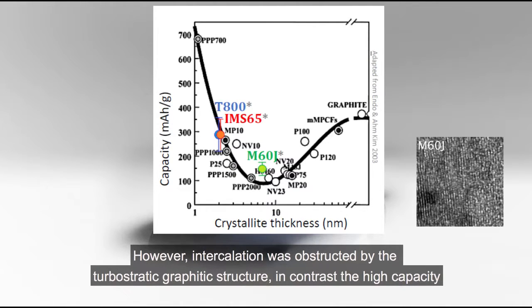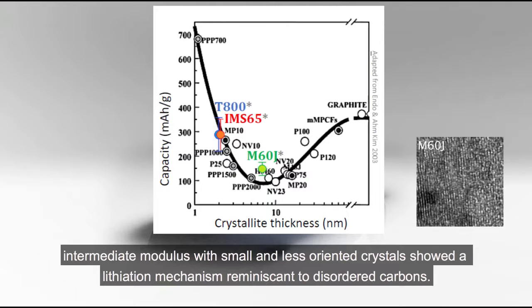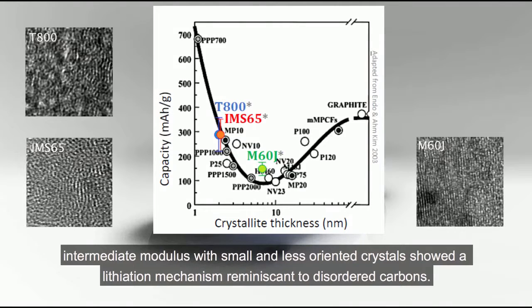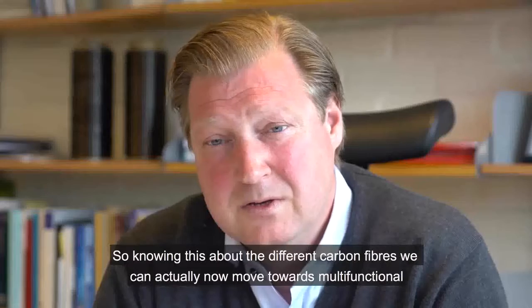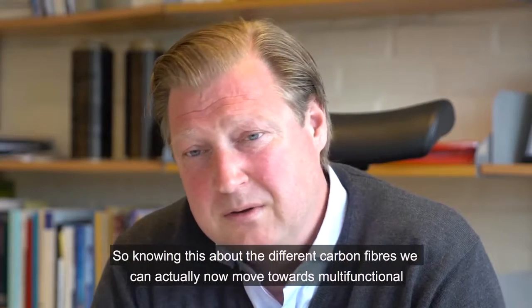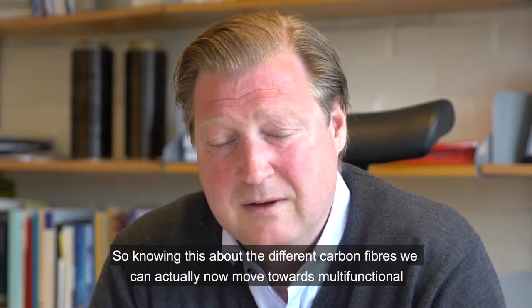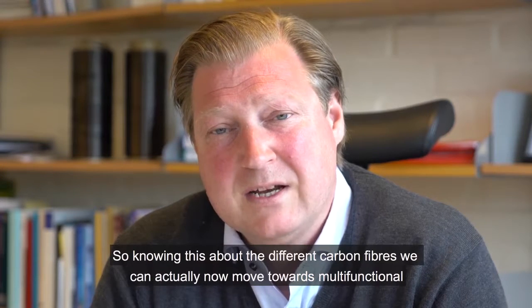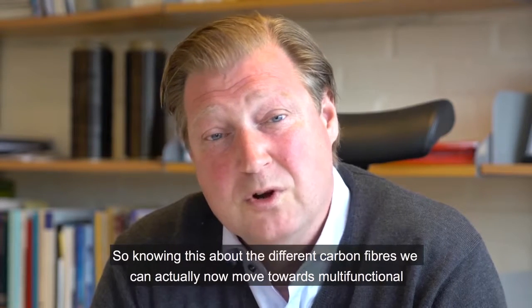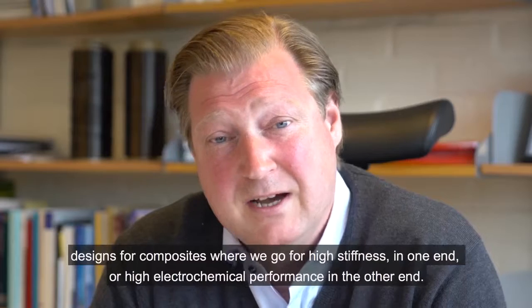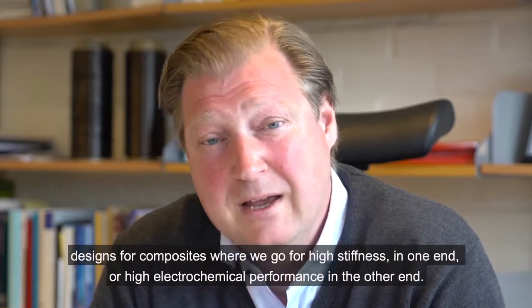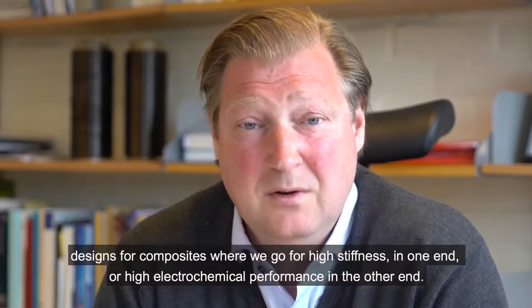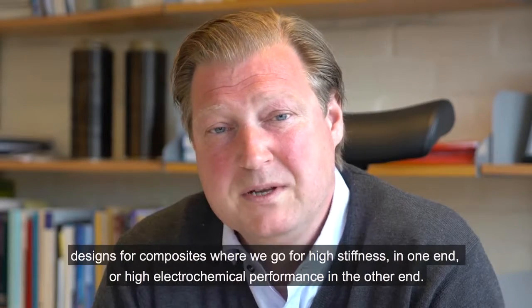In contrast, the high capacity intermediate modulus fibers with small and less oriented crystals show a lithiation mechanism reminiscent of disordered carbons. So knowing this about the different carbon fibers, we can actually now move towards multifunctional designs for composites, where we go for high stiffness in one end or high electrochemical performance in the other end.